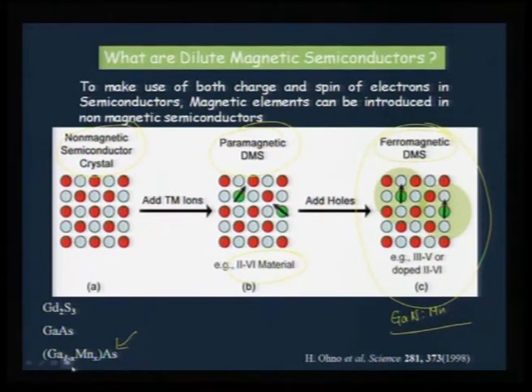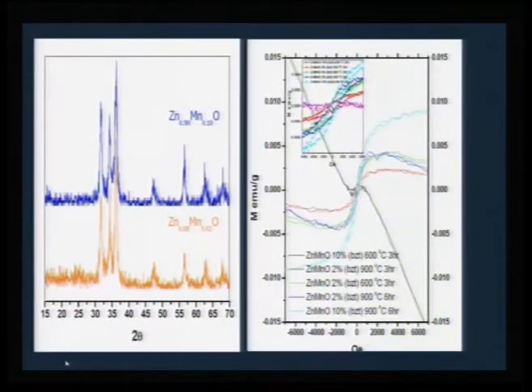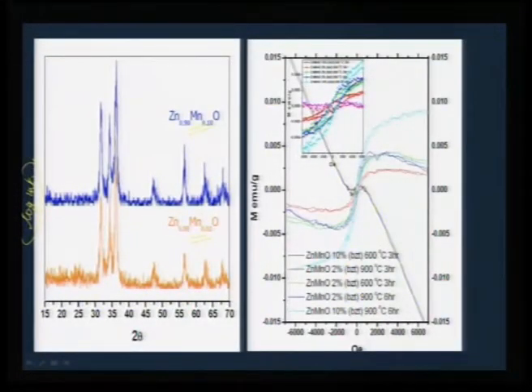Now, we have also taken the same challenge, but we want to incorporate these magnetic impurities exactly in the zinc site in ZnO, and using the solid solution precursor, as you would see here, we can try to get a very highly stoichiometric compound in the form of Zn manganese oxide, which is 2% manganese or 10% manganese. And one important thing is, this is a log intensity plot, that's why you see it too noisy. When you plot it in log intensity, even smaller impurities can be highlighted, and you can see very well here that there is no extra peak even in log intensity, which means even at 10% you don't see any phase segregation of manganese. And this is very important, because this is the first time ever we are able to see such a trend in manganese doped zinc oxides reported either by chemical routes or in thin film form.